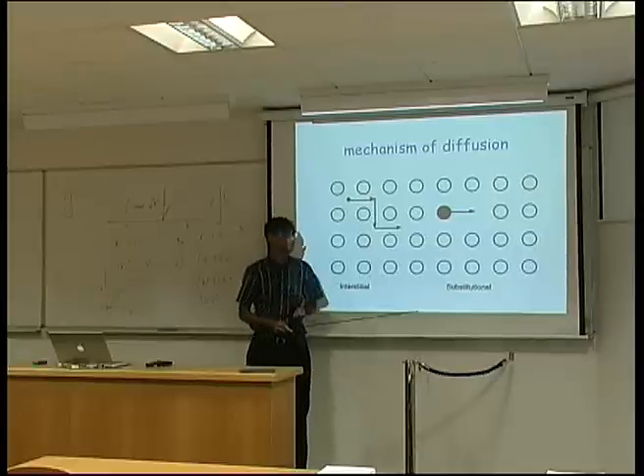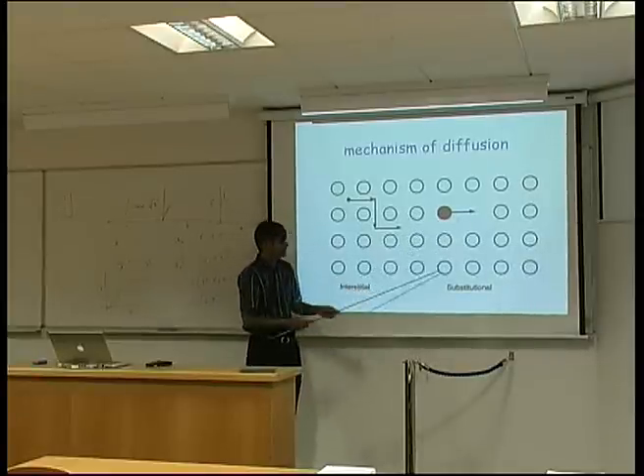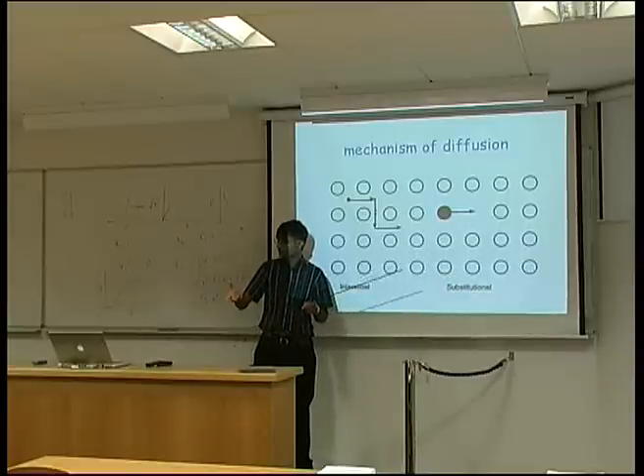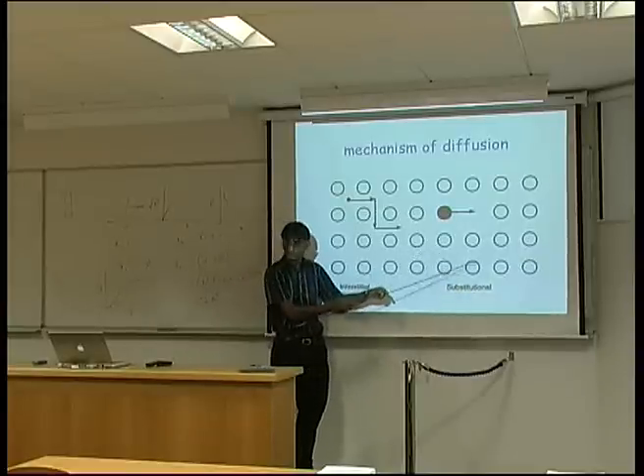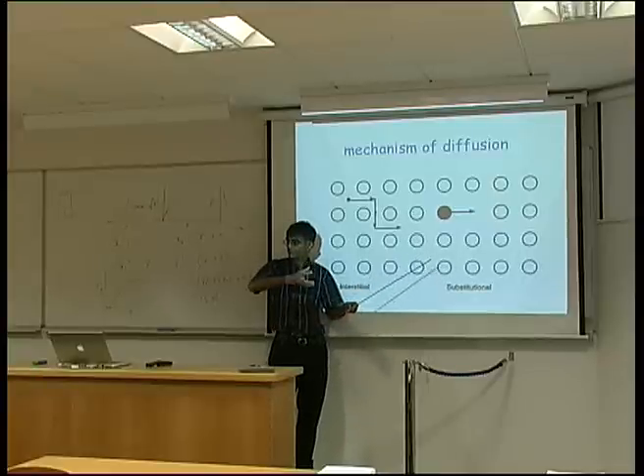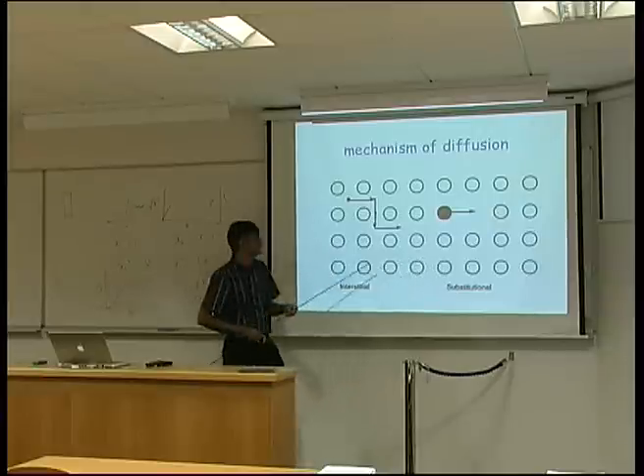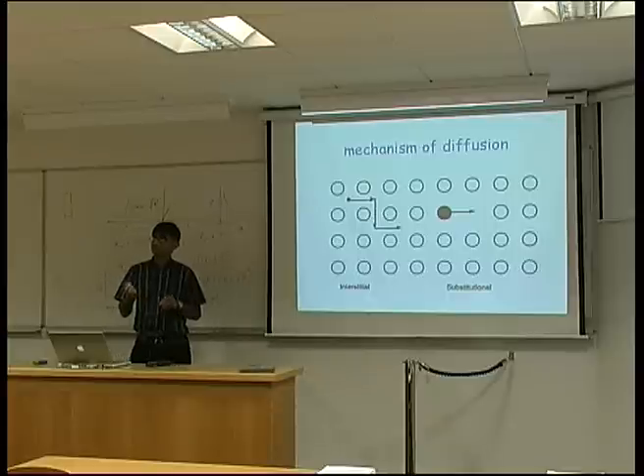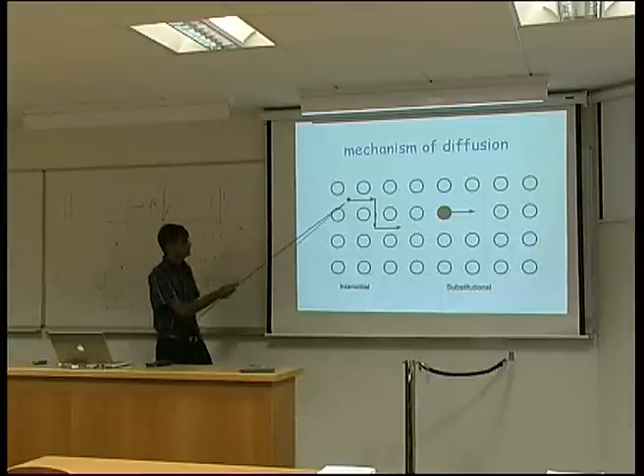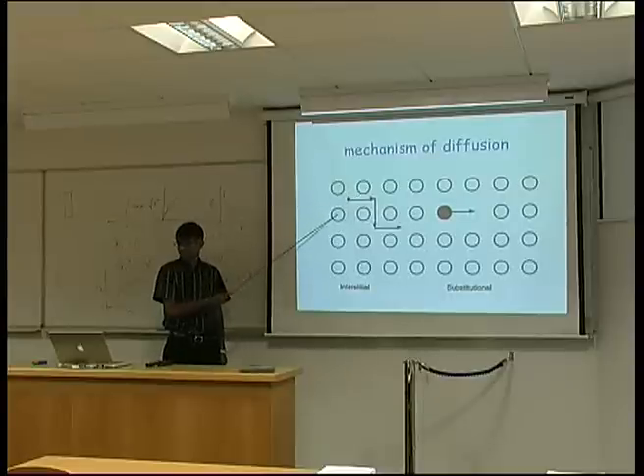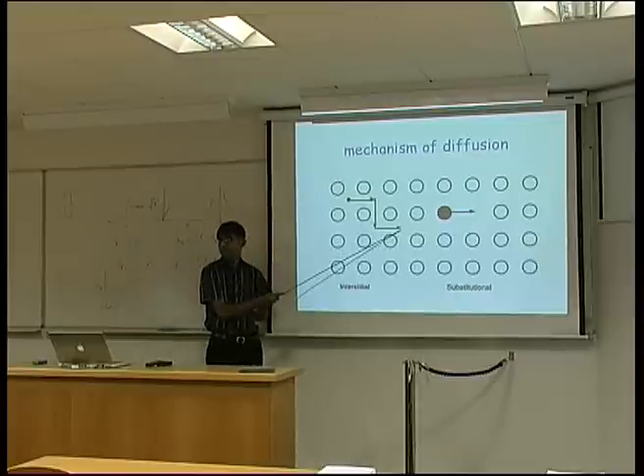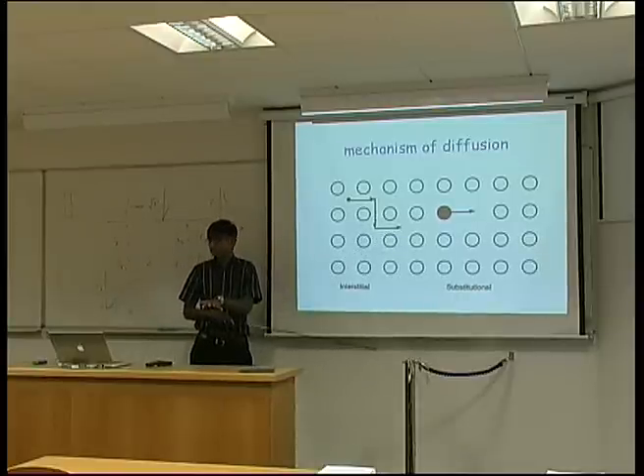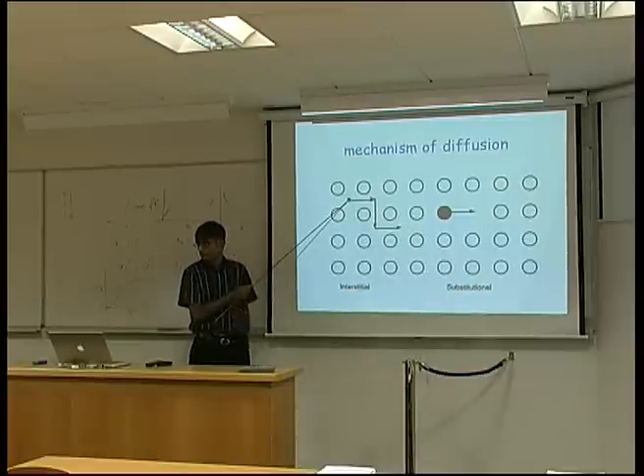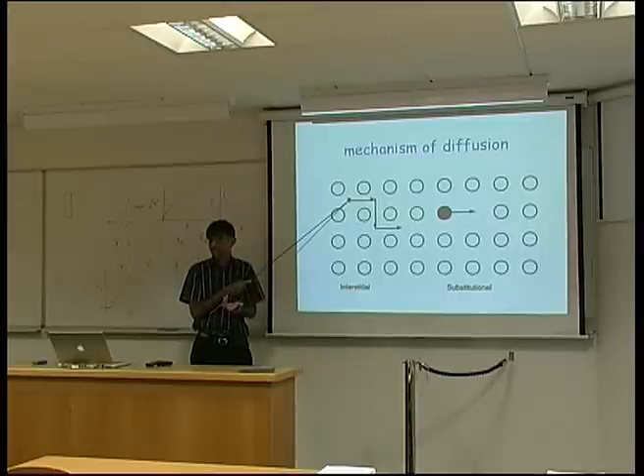We will prove that shortly, that diffusion happens by a vacancy mechanism and not, for example, by these two atoms swapping positions, or even a ring diffusion method where they all jump together and rotate. On the other hand, very frequently we have very small atoms inside the lattice consisting of large atoms. And those small atoms are more comfortable in the interstices. The interstices means the holes between the atoms. And they can move much more readily because there are lots of these channels inside the crystalline structure. So this is called interstitial diffusion. An interstice is simply a hole in the structure.